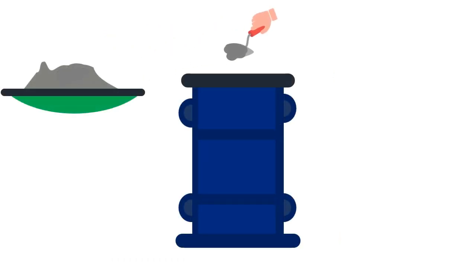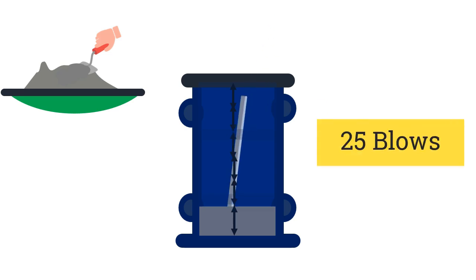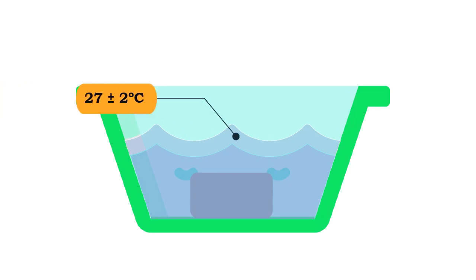The specimen is prepared using the standard manufacturing procedure and placed in the mold in layers, tamped using 25 blows for each layer. After a day, the mold is removed and the specimen is placed in the curing tank.